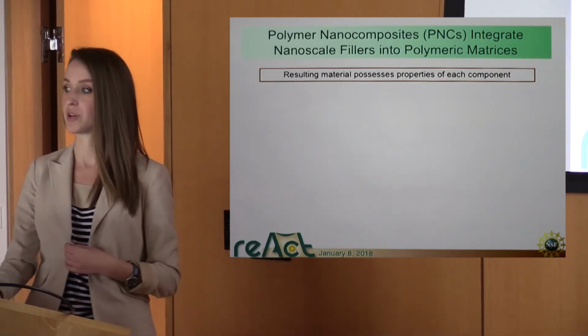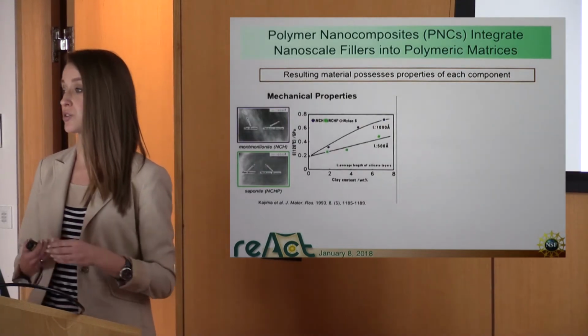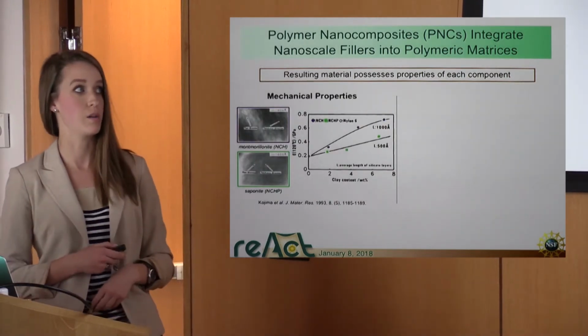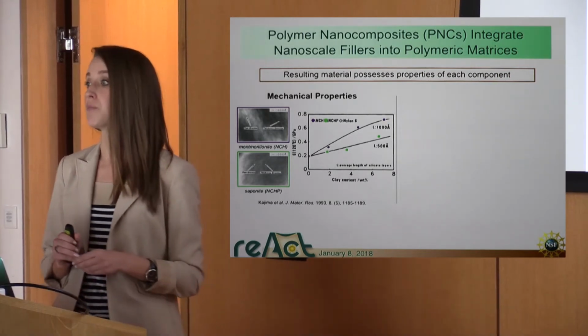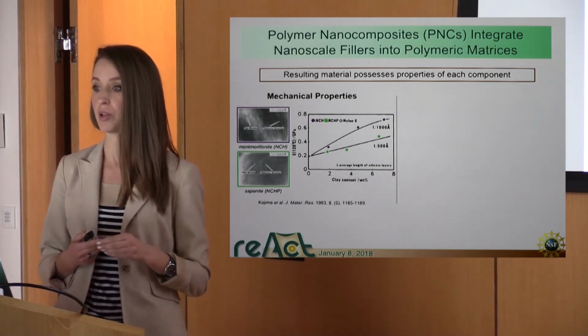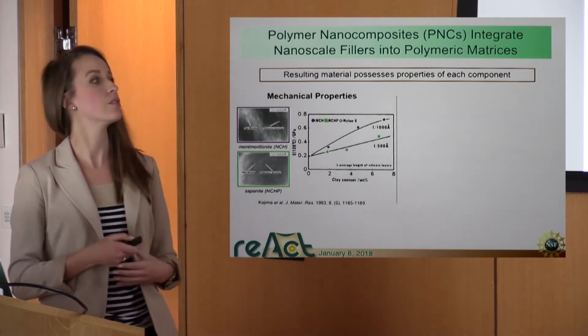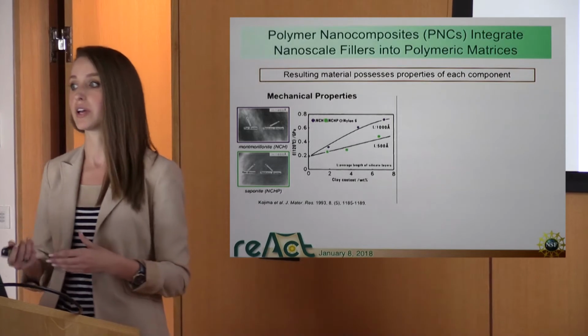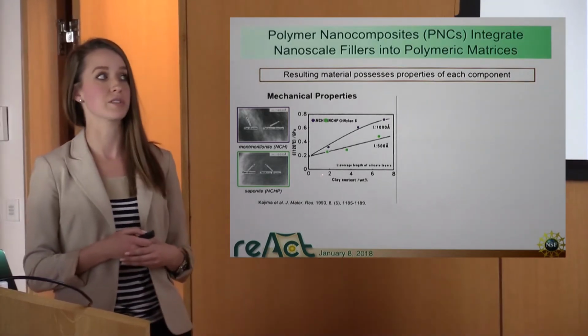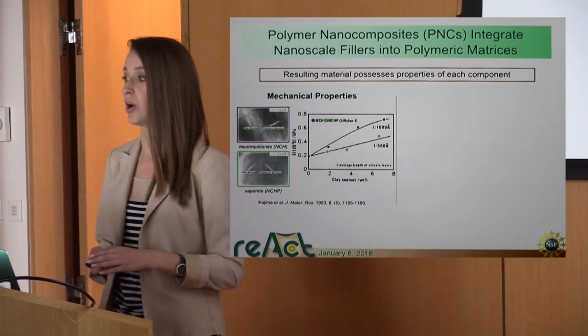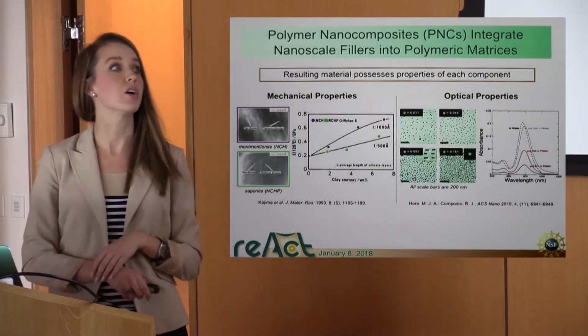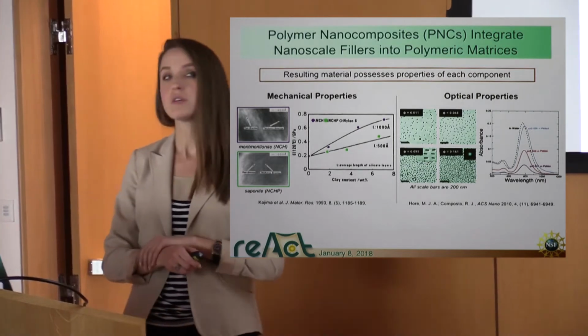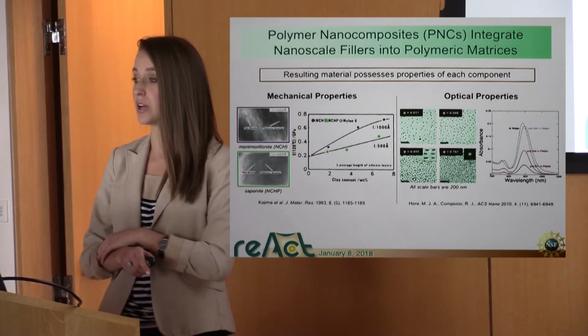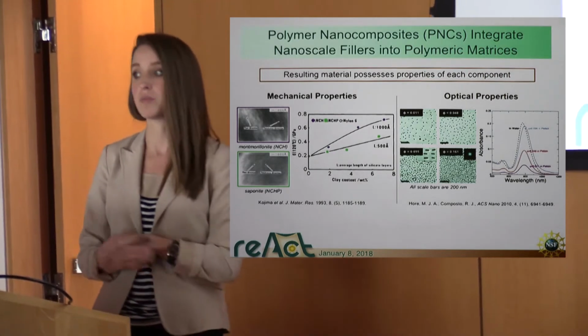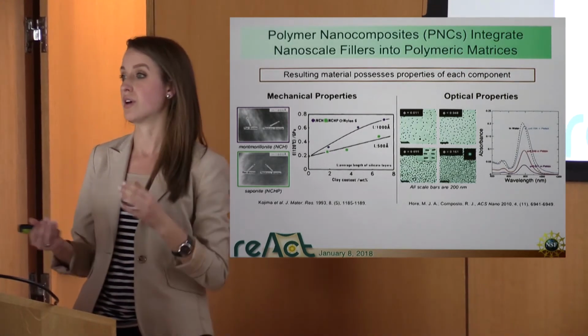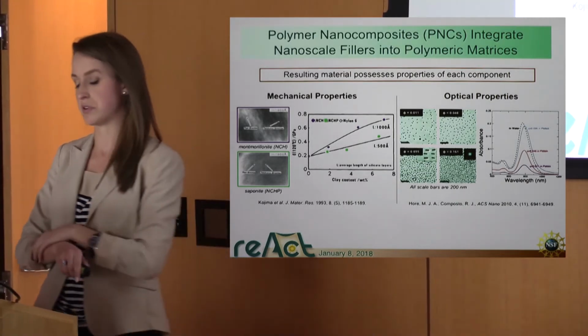So some examples of properties that we can incorporate into a polymer film are mechanical properties. So we can improve the mechanical properties of polymers, where in this case, clay platelets have been introduced into polymeric matrices, and by increasing the loading of the clay or the clay content, we can enhance the mechanical properties compared to the neat polymer system. We can also impart optical properties onto polymers. So in this case, we're incorporating gold nanoparticles into polymeric matrices, and then by increasing the loading and also just the incorporation of these particles, we can impart optical properties into the films.